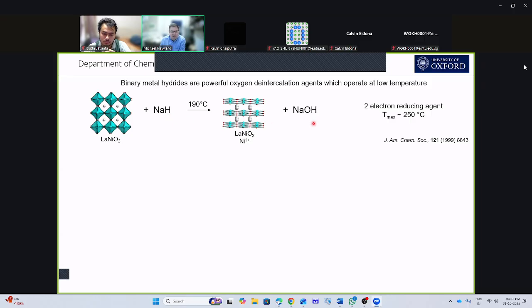It goes from H- to H+. And this is a very versatile reagent. But the problem we have is that sodium hydride enters an equilibrium with sodium and hydrogen at just about 250 degrees C. And so this is the highest temperature we can do these reactions at.